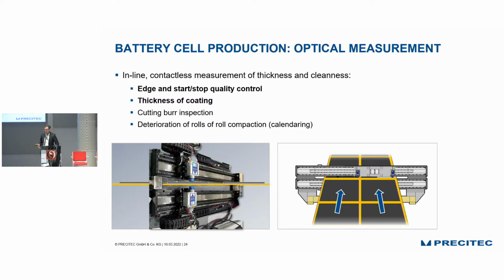Here we have two sensors. One sensor here, one sensor there, working with distance, so no tactile measurement, in a coil-to-coil approach. One sensor at the bottom, one sensor at top, which can measure your thicknesses and can measure your edge and start-stop quality. And not only after calendering and in the dry condition, but also in the wet condition and also on the NMC side. We can measure thickness of coating, cutting burr inspection, deterioration of calendar rolls.